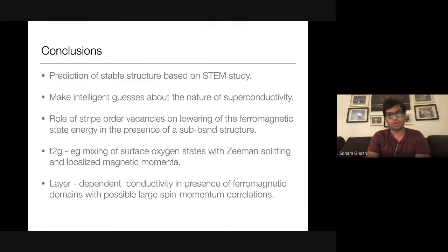So in conclusion, what you can do with DFT and in general condensed matter simulations is you can predict stable structure based on experimental studies. You can make intelligent guesses about the nature of solid states, including superconductivity. You can look at vacancies, their ordering, their stability. You can look at ferromagnetic stability and ferromagnetic instability. You can look at mixing of surface states with bulk states. You can look at splitting, and magnetic moments. And you can look at spin momentum correlations.